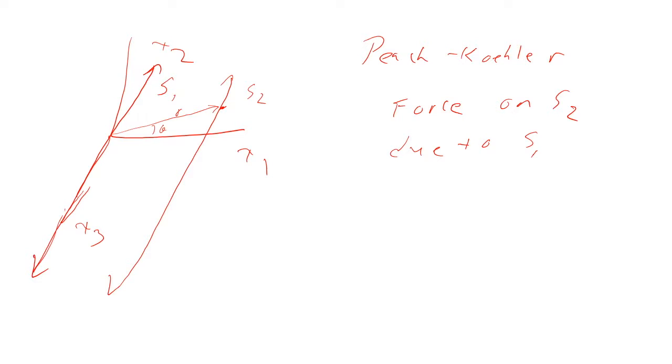But which direction is it going to be acting in? If you ignore the sense of the vector, where is that? Perpendicular to the Burgers vector, yeah. So it has to be perpendicular. The force is always perpendicular to the dislocation line. In this case, it's either going to be in the plane in an attractive sense or a repulsive sense.